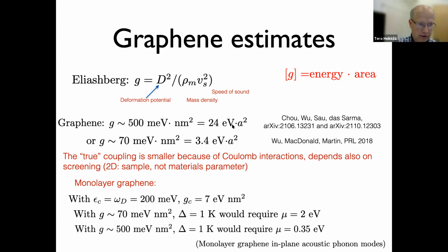But let's take these values and see what would happen in a monolayer graphene. In monolayer graphene, this critical interaction constant is 7 electron volts times nanometer squared. So it is much larger than these G values, which means that at the Dirac point, you are much below this critical point for superconductivity. And therefore, at least at the Dirac point, graphene would not become superconducting.